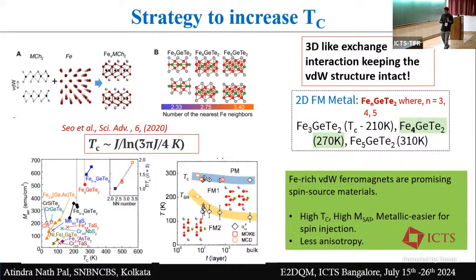Okay. Another interesting observation is that if you decrease the thickness, there are not many experiments, but there is one experiment where they have shown that down to 7 layers, the TC slightly increases. So if you decrease the thickness, you also change the anisotropy, and you can also increase the TC.